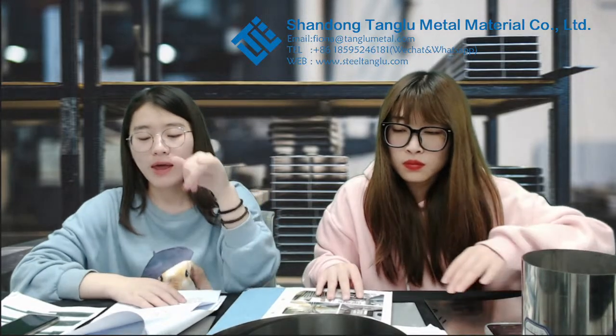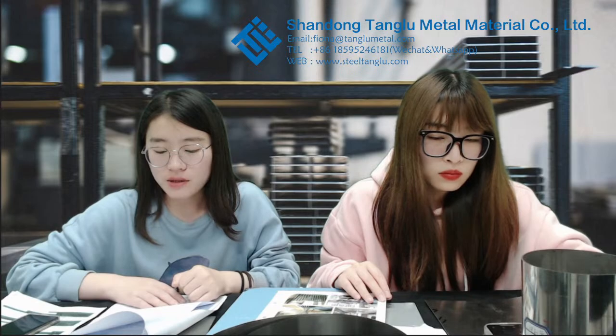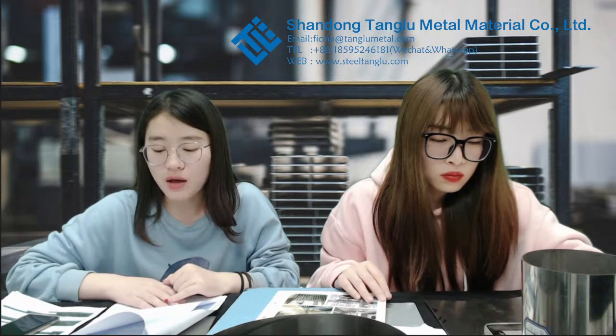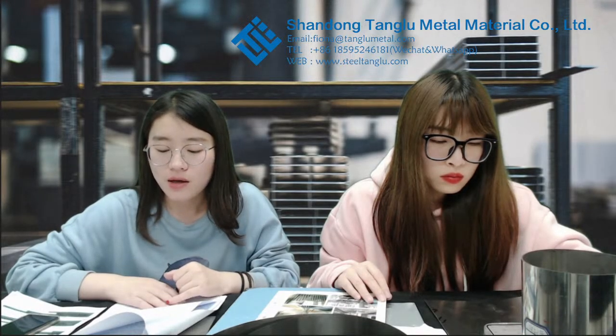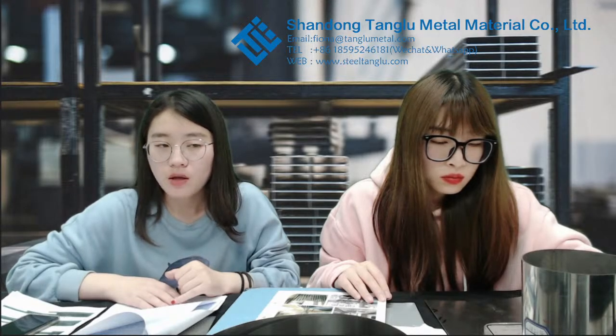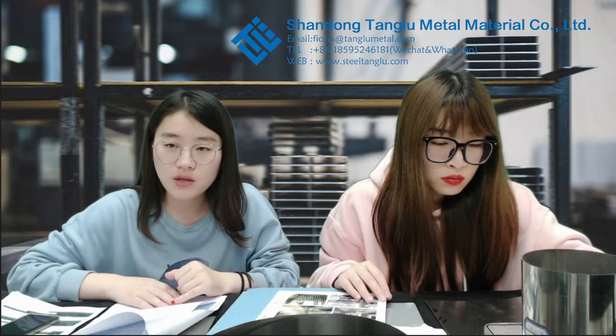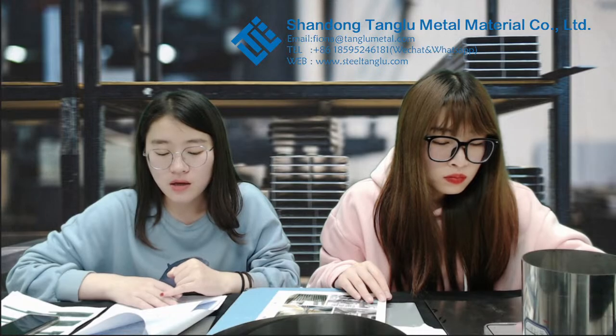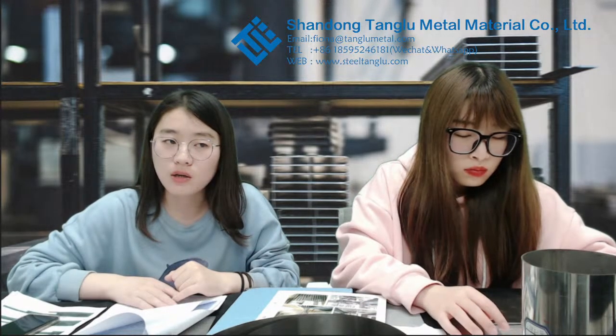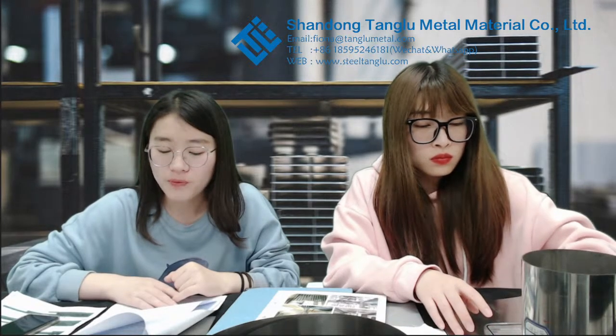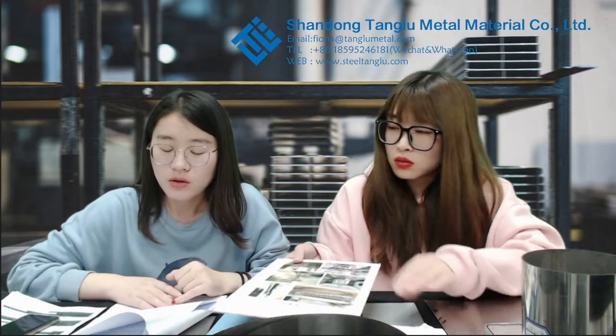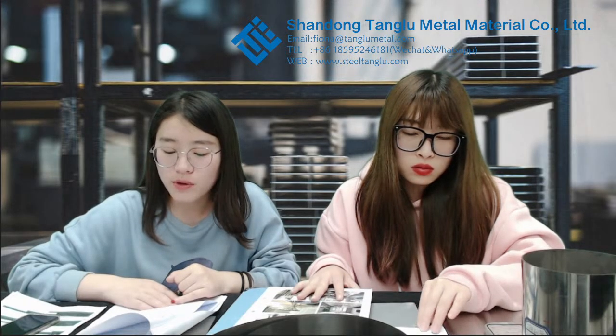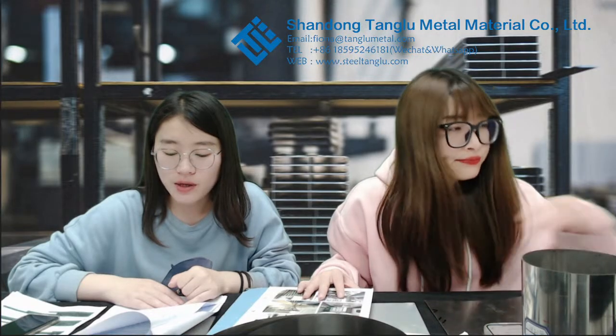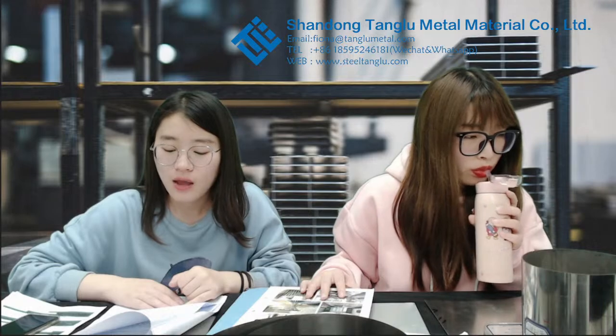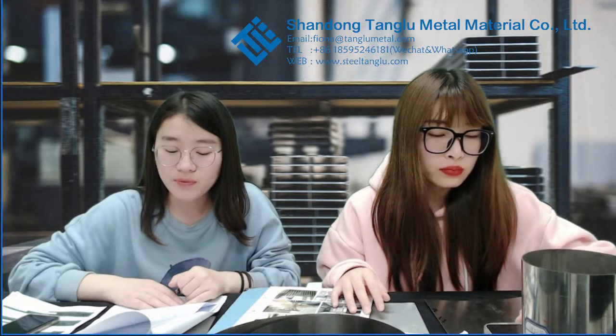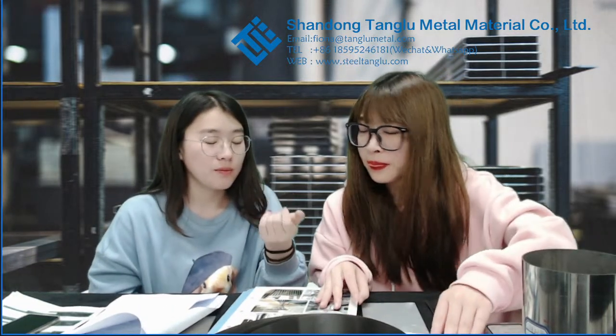Except this 301 has good ductility for molding products. Also, it can go through a hardening process. It has good workability, abrasion resistance and fatigue strength. The fatigue strength is better than that of 304 stainless steel. Okay, the corrosion resistance is lower than 304 due to the carbon content being relatively high. 303 is made by adding a small amount of sulfur to make it better for machining. Okay, next one is 316 material.